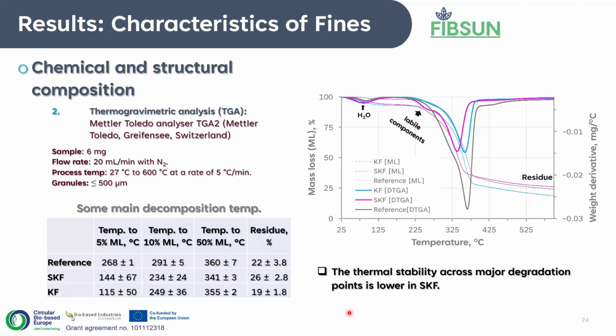But when you talk about the thermal stability of a lignocellulosic material, it's not just about the chemical composition, but it's about the structure in itself. So in the case of wood, the relationship between lignin and hemicelluloses as against celluloses is a more protective factor compared to hemp shives or hemp biomass. So this is why, in any case, we see much better thermal stability for the reference wood